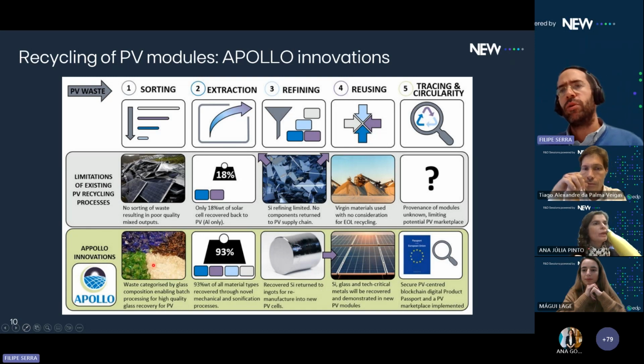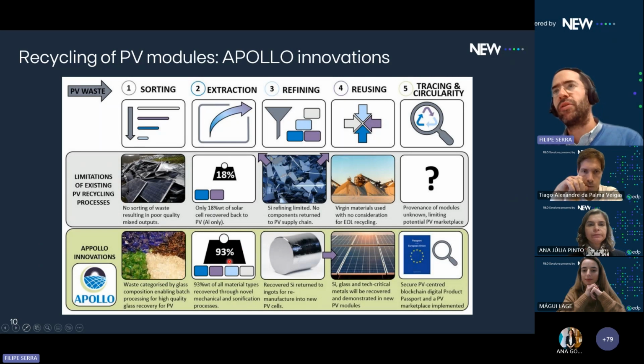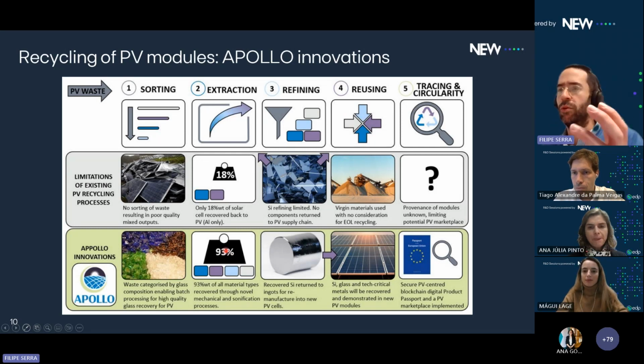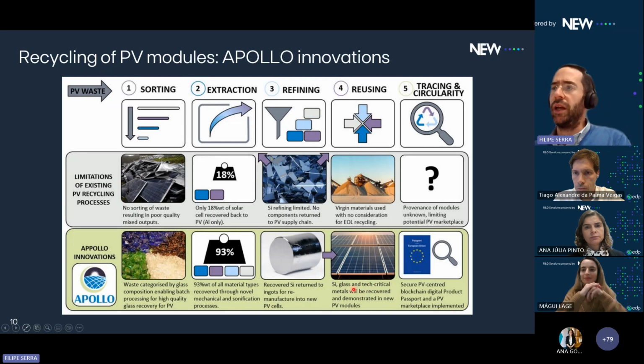So with this project, we want to first categorize waste by glass. Then we want to recover up to 93% of the materials that are in the module. The recovered silicon from the solar cells will then be put back on the silicon feedstock just after the polysilicon production, and in the melt, in order to make the multicrystalline and the monocrystalline silicon ingots, and also the glass and other tech critical materials will be also recovered and put back in their correspondent feedstock.